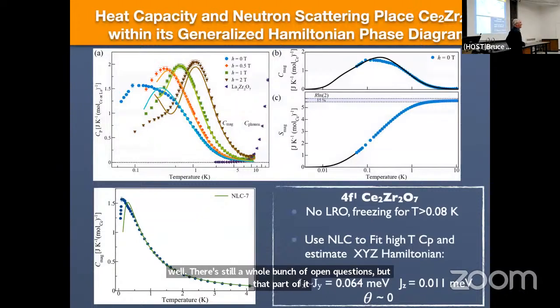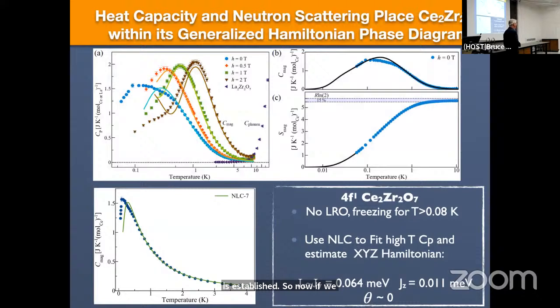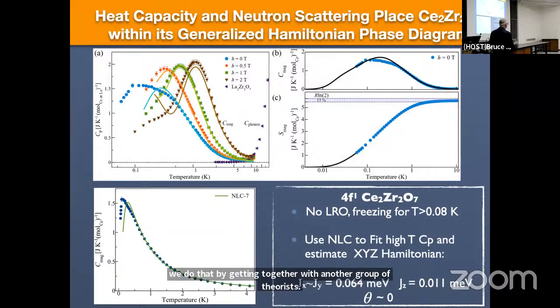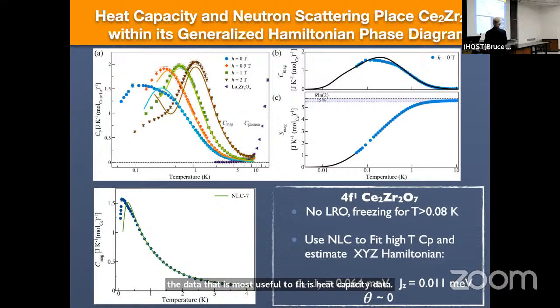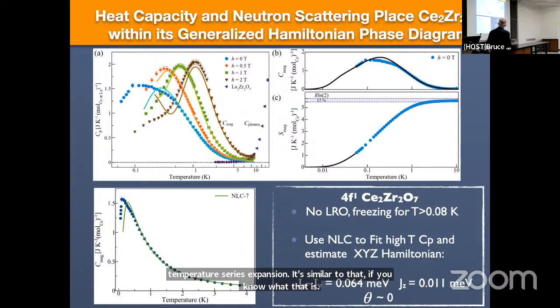So now, if we want to go further than this, actually, how much time do I have? Yeah. 0. 0, okay. So if we want to go further than this, then we've got to estimate the microscopic terms in the Hamiltonian. And we do that by getting together with another group of theorists, okay? The data that is most useful to fit is heat capacity data. And they perform what's called a numerical linked cluster calculation. It's kind of like high temperature series expansion, if you know what that is. At any rate, it's a fit to the high temperature part of the heat capacity. And you can do that in zero field. You can do that in non-zero field. And the net result is that it allows us to estimate the microscopic terms in the Hamiltonian.